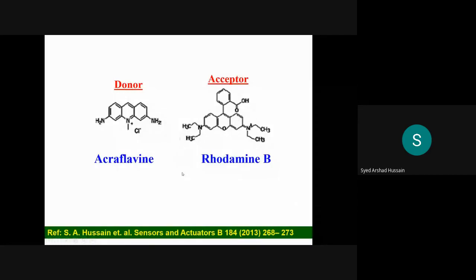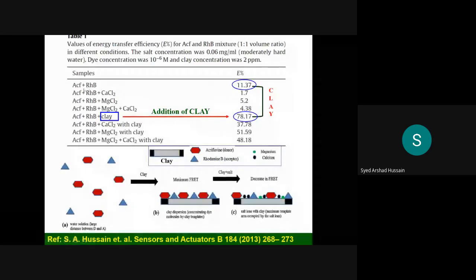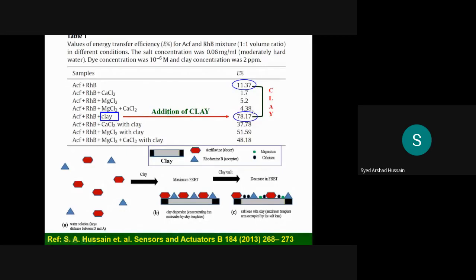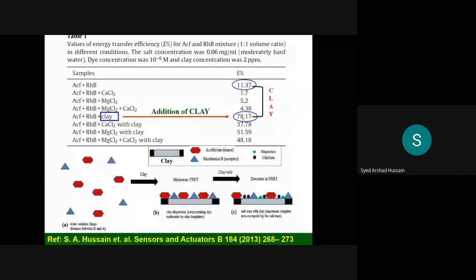These are the two molecules we used for energy transfer. You can see acriflavin and rhodamine energy transfer, this is 11.37%. Then we studied the same in the presence of calcium, magnesium ions. You see energy transfer decreases from 11.37 to 1.7 or 5.2 or 4.38, depending on the presence of calcium, magnesium or both ions. But the decrease is very small. Then what we did, we put some clay in between these two dye systems. Then initially energy transfer increases up to 78. Then we put in the ions, calcium, magnesium or both. Then you see the decrease is from 78 to 37, 78 to 51, then 78 to 48. And these are well resolvable. So here, the presence of clay mainly helps us to increase the sensitivity of the system.